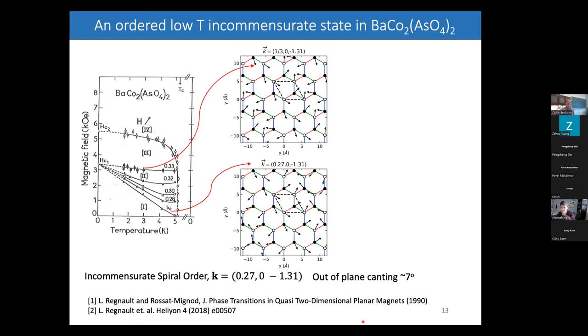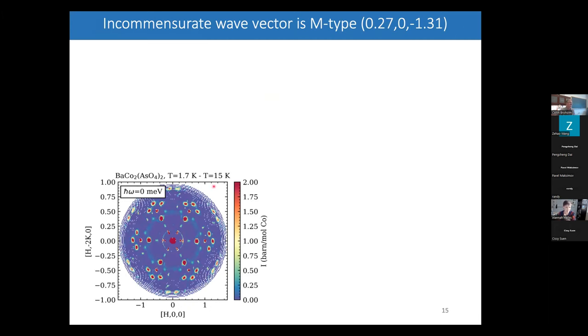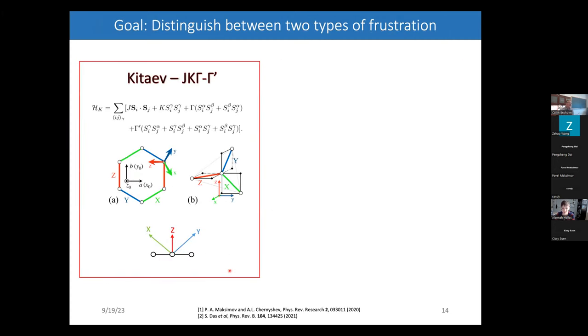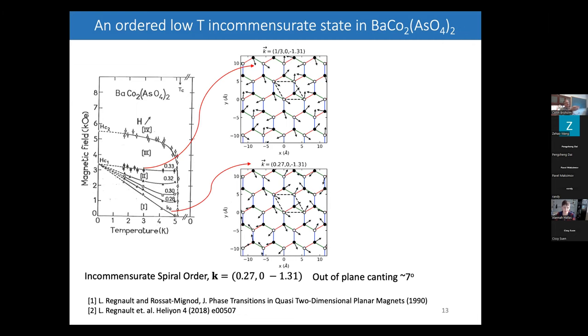Colin, one more question. Yeah. The six satellites that sit around your Bragg peaks, I guess they're all Bragg peaks. Is there some easy way to understand the intensity modulation, that two of them are much less bright than the other four? Yeah, that is fairly straightforward to understand. That modulation is going to tell you something about what happens within the quasi-unit cell. So if I make K to be approximately 1/3, then I have a commensurate unit cell. And basically what's inside that unit cell is what's giving rise to this modulation of the peak intensities.